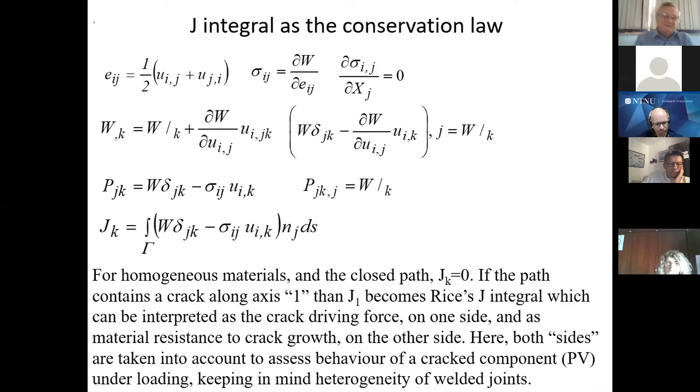But most important in this project, at least from my point of view, is application of J-integral, which was used as a direct measured quantity. But encompassing welded joint, which means that basic definition of J-integral as a conservation law is a bit jeopardized. Actually, according to strict theory, J-integral is not path independent if the path crosses welded joint, because then we have heterogeneous material.